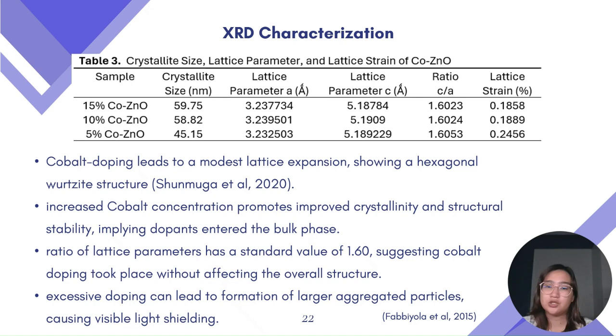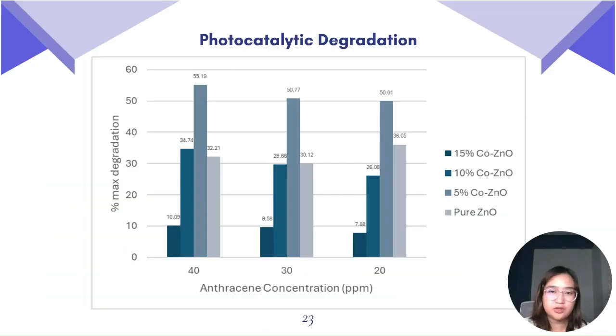There are very subtle changes in the lattice parameters due to substitutional incorporation of cobalt ions, as the cobalt ions replace zinc ions in the crystal structure. The ratio of the lattice parameters has a standard value of 1.6. This is consistent with the values obtained in this experiment, indicating a good correlation and suggesting that doping of cobalt took place without affecting the overall structure. The highest percent degradation out of all the photocatalysts came from the 5% Co-ZnO samples, averaging at around 50%.